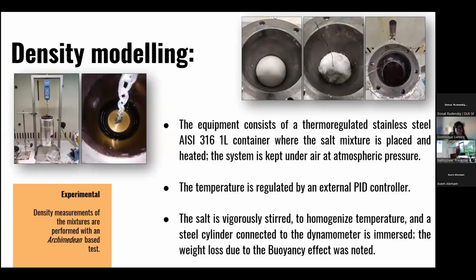validations. So regarding density modeling, we performed a very huge experimental campaign that is very hard to set up at lab scale. Density measurements are performed based on an Archimedean test. These are some pictures of our setup in the lab. So the equipment consists of a stainless steel container where the salt mixture is placed and is kept under air at atmospheric pressure and is heated up.